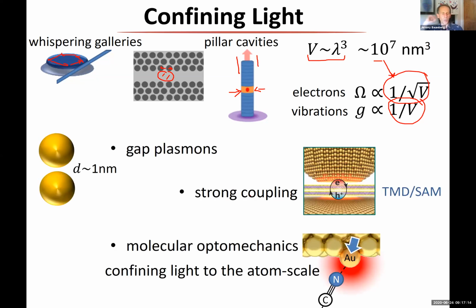So this is why I'm going to really talk today about plasmons. And as I'll show you, plasmons allow you to go deep below this wavelength cubed scale. So I'll show you something where you can confine plasmons into these very tight gaps here, where the gaps are on the order of nanometers or even less. And I'll show you how then you can get strong coupling in this sort of system and in molecules or in these 2D semiconductors. And then what I'll really try and show you is where we're going at the moment, which is trying to understand where I can go even tighter confinement, and I can confine light down to the atomic scale, and what we're starting to understand about that. So that's a really interesting system.